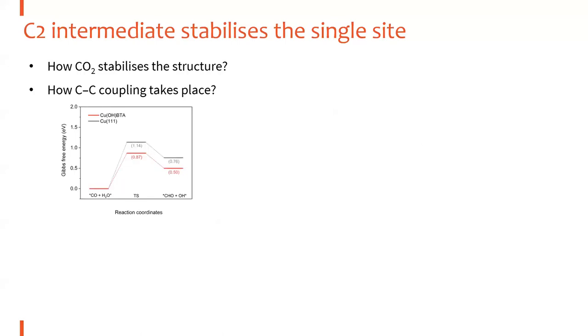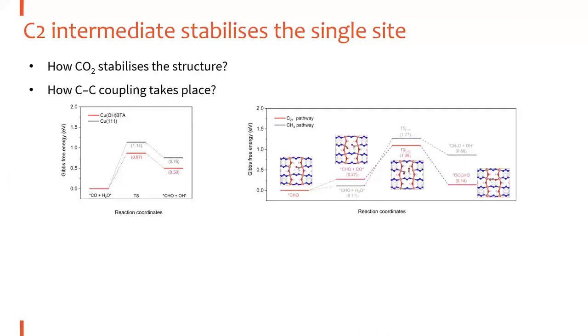The DFT collaborators helped us calculate the reaction pathway on computer, and they found that the rate determining step, which determines how fast the reaction can go, is actually the CO hydrogenation step to form CHO. After the formation of CHO, they found that the coupling of CHO on one copper atom with a CO intermediate on its neighboring copper atom is the most energetically favorable way to form an OCCHO intermediate. The OCCHO is the intermediate towards the C2 pathway. Once you form this, all the reaction steps afterwards are downhill, so I do not show them here. So we can understand that C-C coupling actually happens on two neighboring copper atoms.